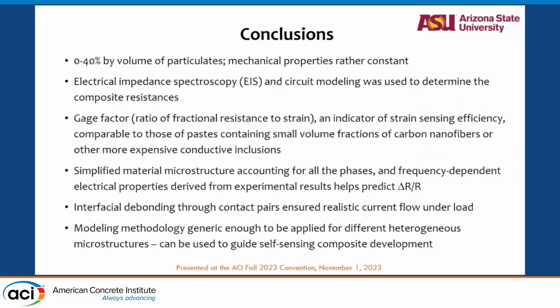So the conclusion is that up to 40% of iron powder did not show significant reduction. At least with flexure it showed improvement in the flexural strength, while for compression it was not a significant decrease. This embedded iron powder itself could give us a stress state. Initially the gauge factors need to be figured out, but once that's figured out, you could use this system inherently to get the stress states from the strain and stress that is being faced at the point of test.